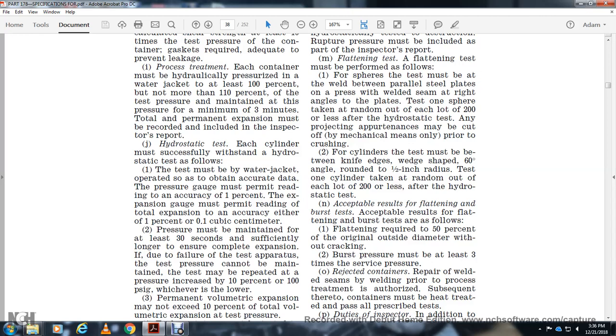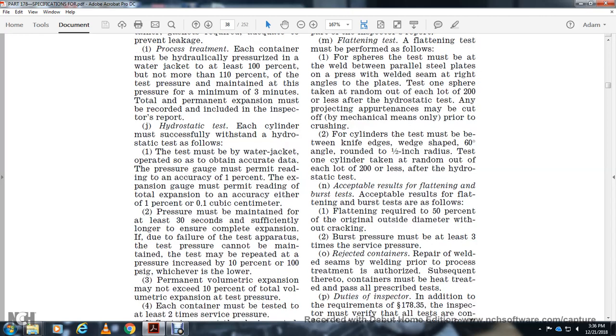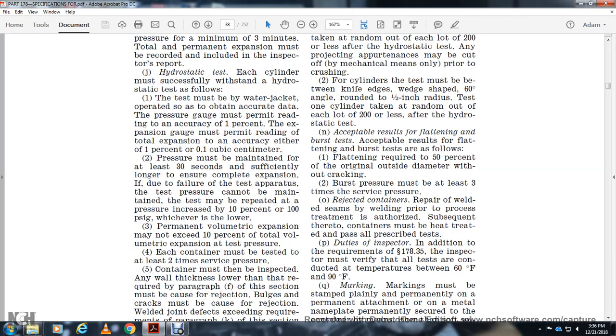If the test pressure cannot be maintained, the test must be repeated with the pressure increased by 10% or 100 psi gauge, whichever is lower. Permanent volumetric expansion may not exceed 10% of the total volumetric expansion. Each container may be tested at least 2 times the service pressure. The container must be inspected.